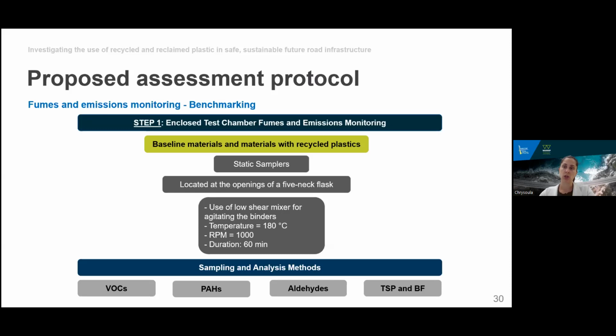Following these trial methods, we were able to put forward an assessment protocol, which would allow for an initial benchmarking activity using the enclosed chamber method, and a method for the assessment of fumes and emissions in a laboratory environment as experienced by the operators and others potentially working near these workstations, which can be assessed against Safe Work Australia limits. As a first step, baseline material and binders containing recycled plastics can be comparatively assessed in an enclosed chamber. The temperature of 180 plus minus 10 degrees, which is typical for blending polymers in the laboratory, is recommended here, even for the base bitumen, just for a better comparative analysis. We found that all target fumes and emissions could be assessed this way, although we do recognize limitations relating to oxygen flow and availability within the chamber.